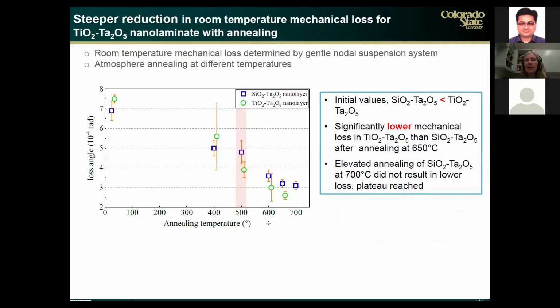So in this particular case, there is mixing and homogenization. We measured the mechanical loss of these samples. Actually, our colleague Gabriele Vajente measured these and obtained these results, plotted here. We plot loss angle as a function of annealing temperature. The green dots are for the titanium tantalum nanolaminate. The blue dots are for the silica tantalum nanolaminate. What you see here is that both nanolaminates have very similar values of the loss angle for the as deposited sample. But when we start annealing, we see a sharper decrease in the mechanical loss in the titanium tantalum nanolaminate compared to the silica. And for the silica, when we get to about 650 degrees C, the mechanical loss does not decrease any further.